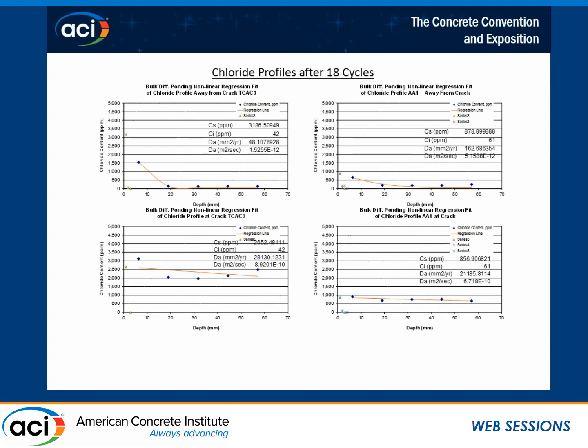Looking at a couple of others here, the calcium aluminate cement we had. Initially it looks a little bit like it's doing diffusion, low chloride, low value, just like the OPC. Actually, maybe a little bit lower than OPC was. When it cracked, once again, you get a little bit of a drop, but basically pretty much uniform and 1.5 orders of magnitude higher. So it's definitely hurting at the cracks.